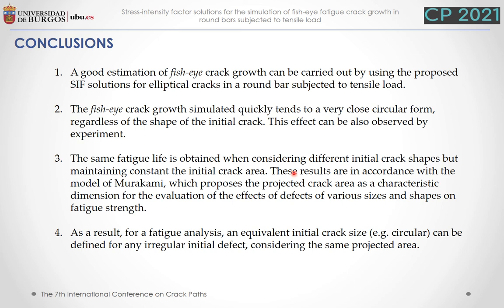The main conclusions of this paper are: A good estimation of fisheye crack growth can be carried out using the proposed stress intensity factor solution for elliptical cracks in round bars subjected to tensile load. The fisheye crack growth simulation quickly trends toward a circular form regardless of the initial crack shape, an effect also observed experimentally. The same fatigue life is obtained for different initial crack shapes when the initial crack area is maintained constant, in accordance with Murakami's model proposing the projected crack area as a characteristic dimension. Finally, an equivalent initial circular crack can be defined for any irregular initial defect considering the same projected area.